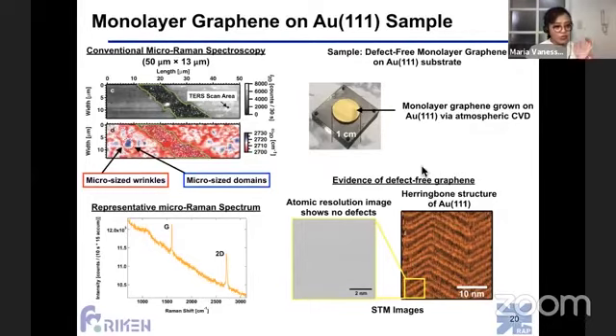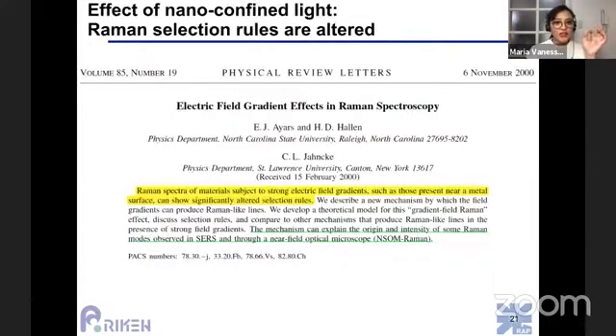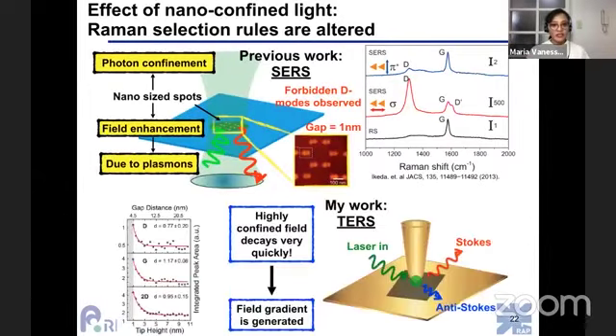The very nice thing about not only having high spatial resolution is we found that if you have highly confined light, you can alter the Raman selection rules. This means that you can maybe even change the chemical sensitivity of your system. This was shown using surface enhanced Raman spectroscopy, which is diffraction limited. The results by our collaborator showed similar work wherein they were able to observe what we call forbidden modes, which are associated with defects on graphene, but their sample did not have any defects. It's a pristine sample, but they were still able to observe these peaks. And the main question is why?